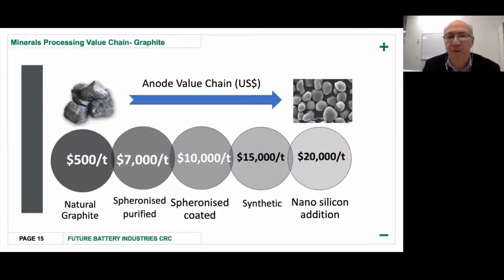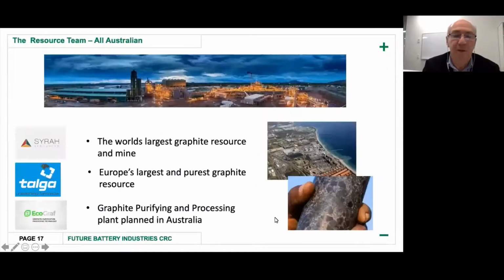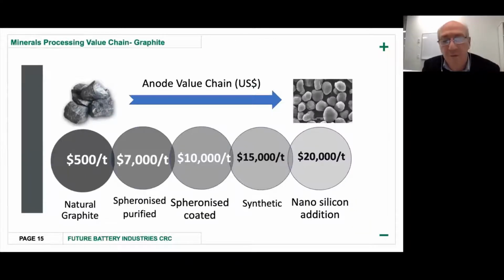If we've looked briefly at the value chain, but if we go back and look at the stages of processing for this material, we find that we start with natural graphite. Oh, excuse me, let's go back one slide. We start with natural graphite and we take it through a spheronizing process and purifying. We then need to coat that material and we can hybridize it with synthetic graphite. It's important then that we integrate this material with nanosilicon addition. And the way that we do this increases the performance of the anode significantly.